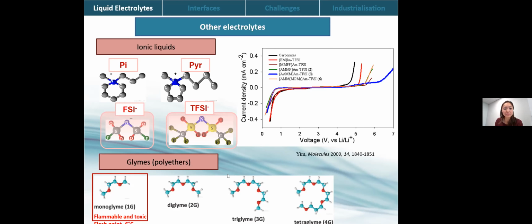Then we have the glymes. They are called polyethers. They are also called glymes. Here I show a range of glymes. Basically we call them monoglyme, diglyme, triglyme, and tetraglyme. For the glymes, we have to be careful when using them because especially monoglyme is flammable and toxic, and it has a very low flash point of -6 degrees Celsius. It is widely tested and used in lithium metal or lithium ion batteries.